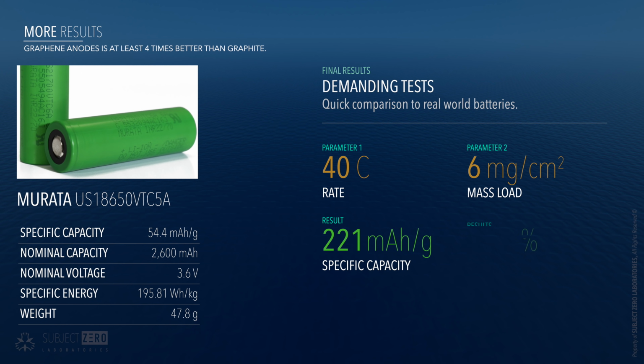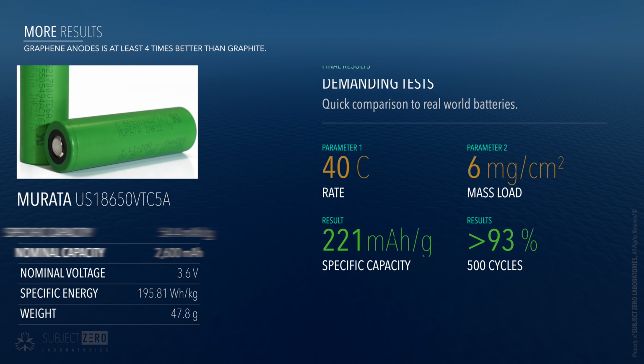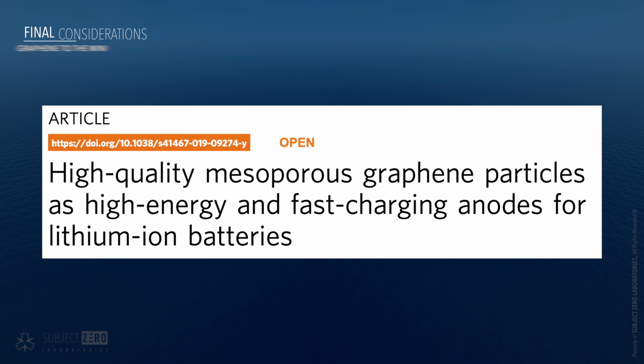On top of all of that, it still was able to retain more than 93% of its capacity after 500 cycles, where conventional batteries will disintegrate if you do 500 cycles at 40C. So yes, this is amazing. This research pretty much confirms graphene as a major player in future battery technology. Now, I would go as far as saying that it will most likely increase battery specific capacity by 4 times at least, but to be sure, we will have to wait for the first batteries to come out to see if this holds true. Fingers crossed.